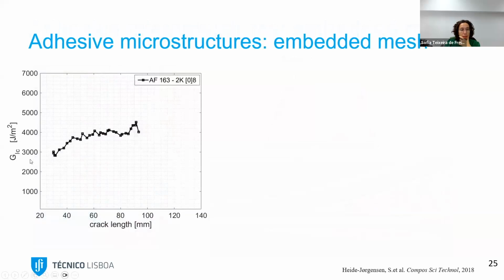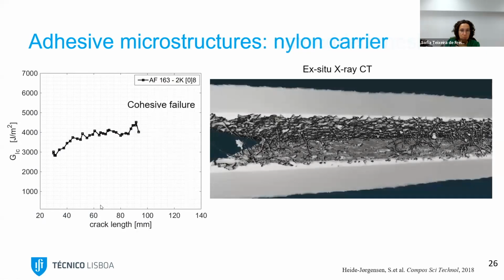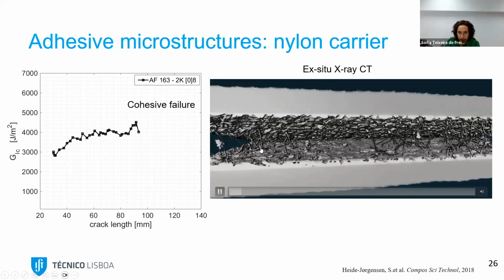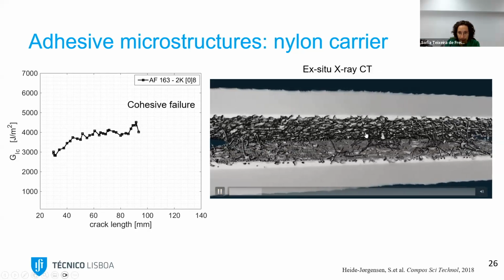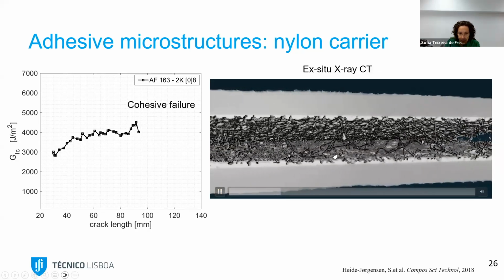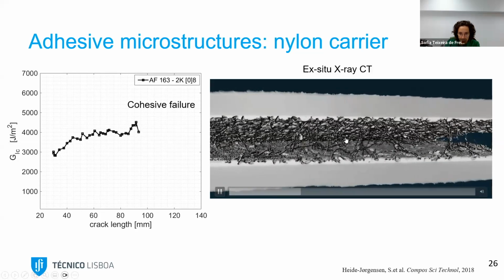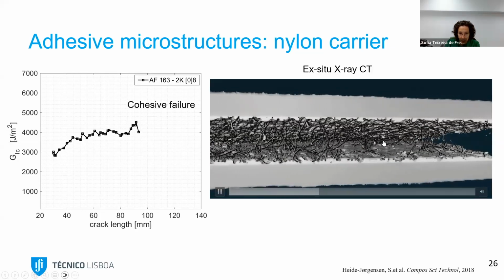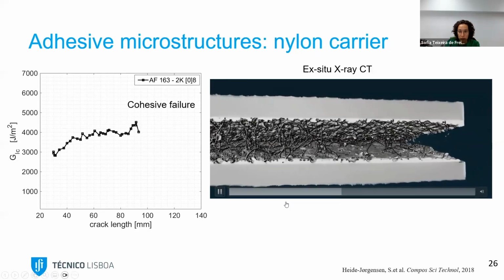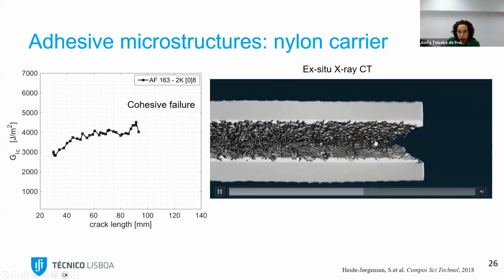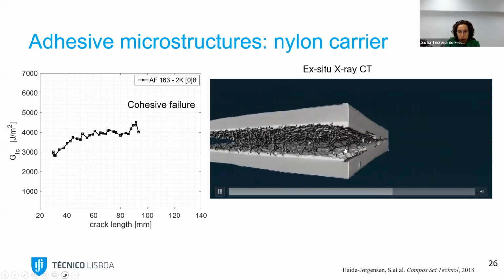What we see here is that we have, again, the same graph that I was mentioning to you. So the fracture toughness, the energy release rate, against the crack length. And we had to look closer also to the X-ray CT, and you see all these nylon fibers connecting the two substrates in a significant amount of locations within the adhesive. So because they create this bridging between the two substrates,